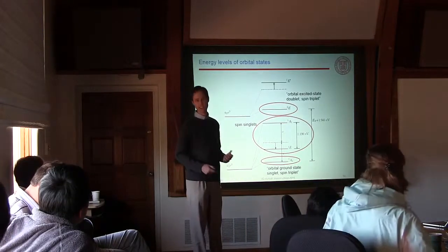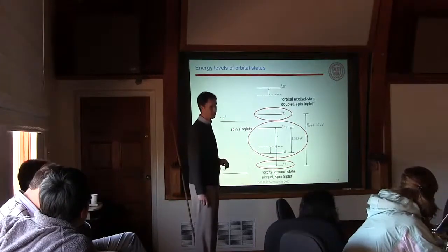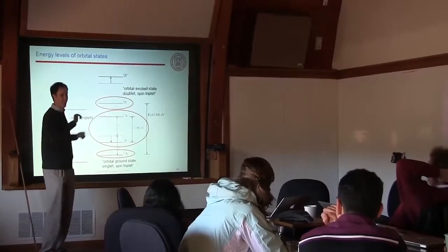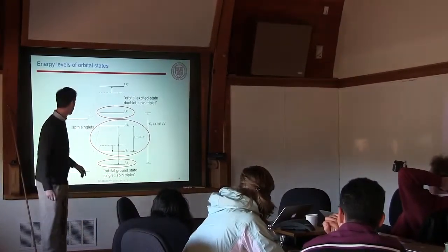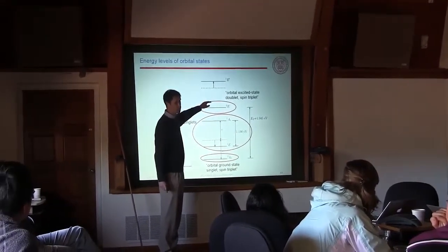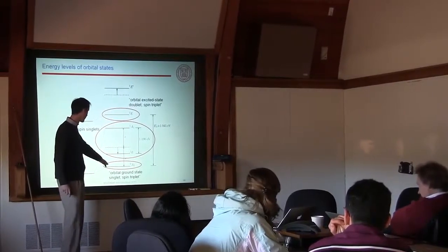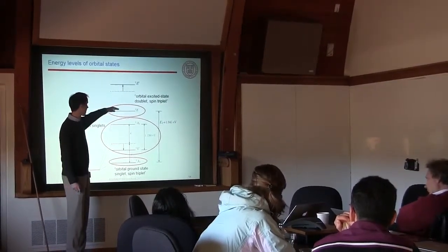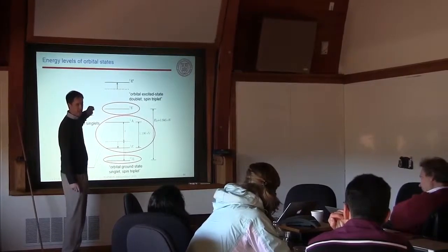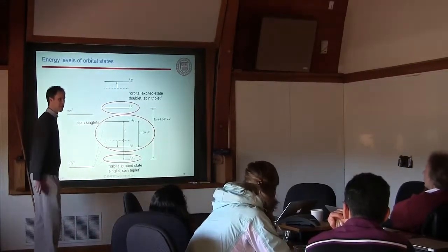This just underscores that there are still open questions about this extremely well-studied system. How much of the spin state is known in the optical excitation? I have a paper on that. As far as we know, the optical excitation between the ground state and the excited state preserves the spin state perfectly, up to the fidelity of our microwave pulses. What we did was prepare a superposition state here, excite, and then measure it up here, a kind of tomography experiment, and we find its fidelity is as close to one as we can achieve. So it doesn't seem to matter.